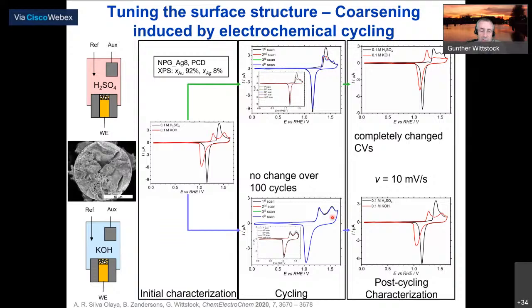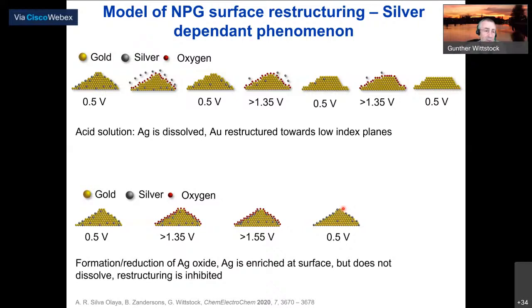peak is gone. So in combination with XPS analysis, we attribute that peak to silver species, which is on the surface of that and is removed in the first exposure in sulfuric acid to positive potentials, but it can stay there in alkaline solution. So the process which we think is like this. So we form an oxide, then silver is dissolved, and surface oxide pulls the silver atoms to the surface, and step by step we basically deplete the surface in silver. And there's quite a mobility of the atoms.